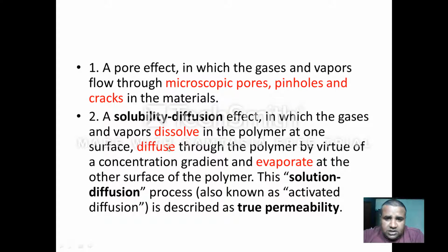First they dissolve, then they diffuse, and how do they diffuse? They diffuse by virtue of the concentration gradient, and finally they evaporate at the other surface of the polymer. So first they dissolve, then they diffuse, and finally they evaporate.